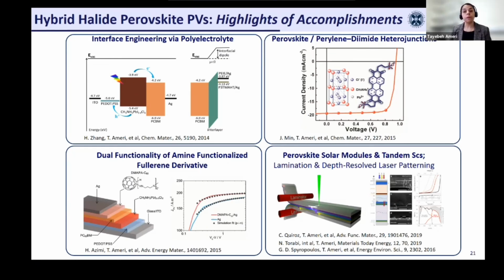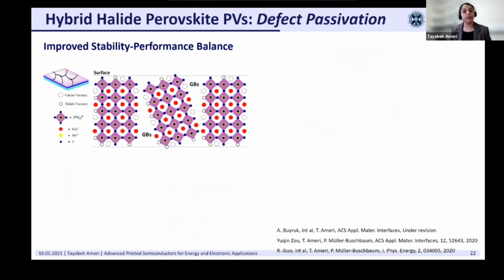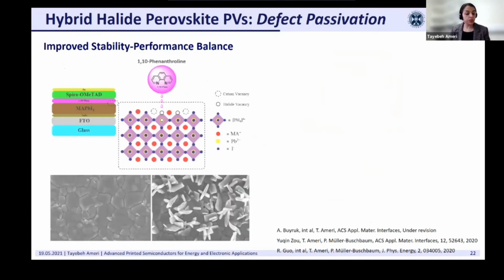One of the topics that is very active right now in my group is defect passivation. As already mentioned, it's a crystalline material, and when we are processing it from solution at room temperature, we are forming a polycrystalline film with a lot of defects on the surface and the grain boundaries. So what we are trying to do is to introduce multiple ligand Lewis bases to passivate these defects.